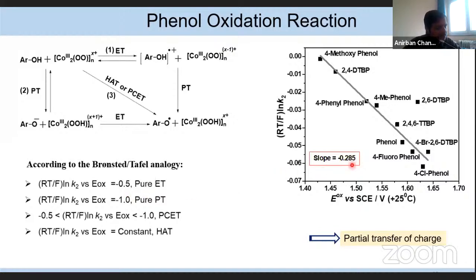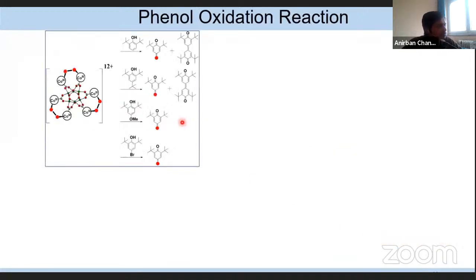However, there is a paper from Professor Karlin and also Fukuzumi, where they already mentioned that such a lower value of the slope can be possible, and this happens when the proton transfer from neutral phenol to the end-on peroxo species takes place via the concerted electron transfer proton transfer pathway. But here there is no complete transfer of charge taking place, it occurs via partial transfer of charge. So here I conclude also that for my end-on peroxo intermediate 2, the phenol oxidation takes place via partial transfer of charge.